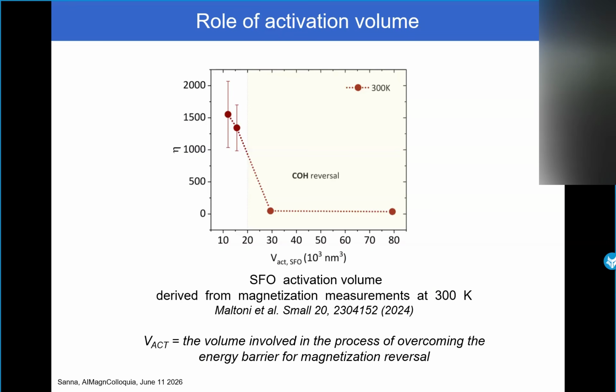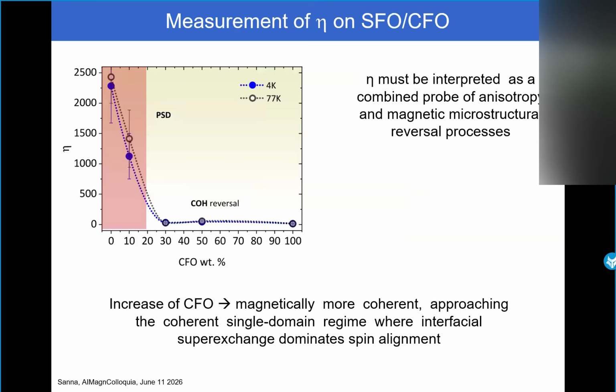of the dimensions of the grain size of the materials, which means that we discovered a method to measure the effective coherent magnetic activation volume in nanoparticles when we want to distinguish with respect to incoherent magnetization in the system. Okay, so at the end, it means that increasing the CFO content, we have a magnetically more coherent condition approaching the coherent single domain regime where interfacial superexchange dominates the spin alignment.